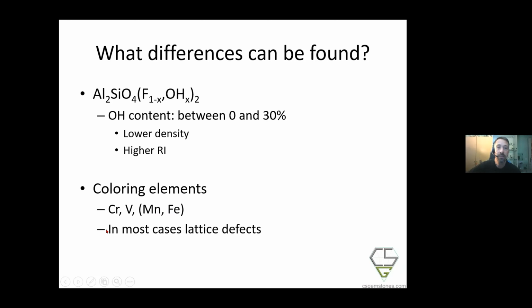But in most cases in topaz, we have lattice defects. So we have some holes in the lattice where some elements should stay, or we have some trapped oxygen atoms. We have oxygen with strange oxidation states or not typical oxidation states. And these lattice defects cause most of the colors in topaz. They cause the yellow, they cause the brown, and they cause the blue.